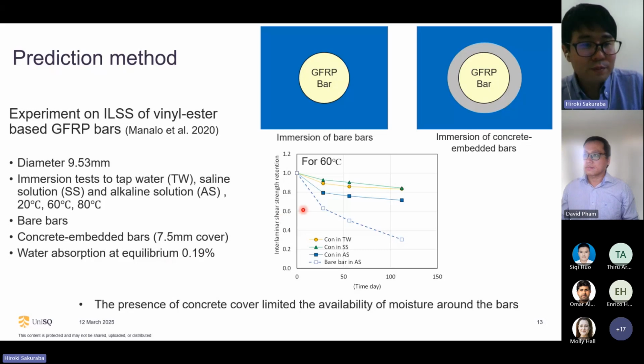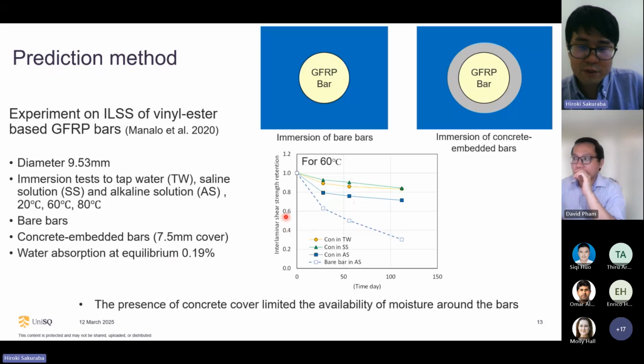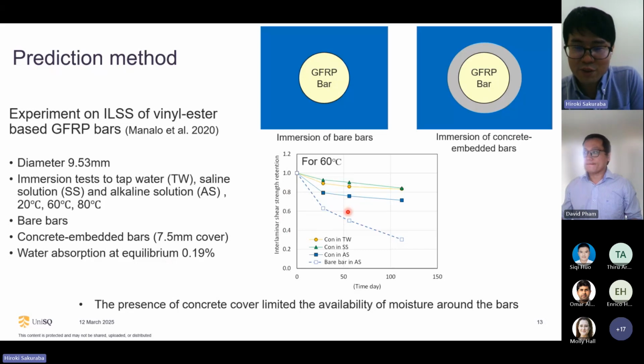So this is an example of an immersion test using concrete embedded bars and bare bars. The vertical axis is ILSS retention. This means conditioned interlaminar shear strength divided by unconditioned interlaminar shear strength. So as you can see, if we use bare bars, the ILSS retention is reduced rapidly. But if we use concrete embedded bars, ILSS will have higher retention. This is because the presence of the concrete cover limited the availability of moisture around the bars. So the concrete cover has a really important role for the durability of GFRP bars.